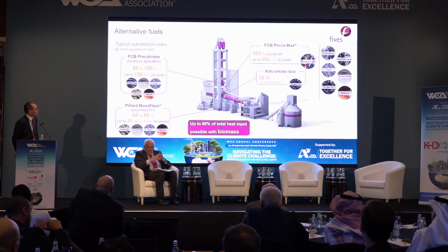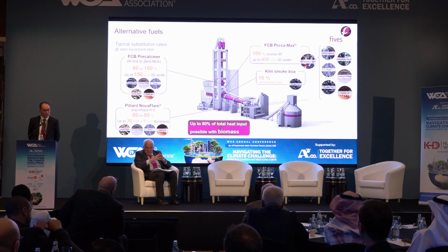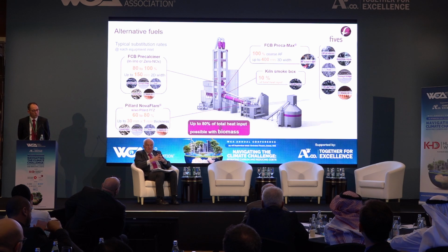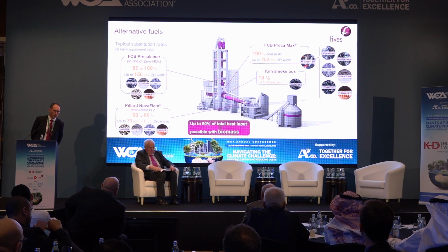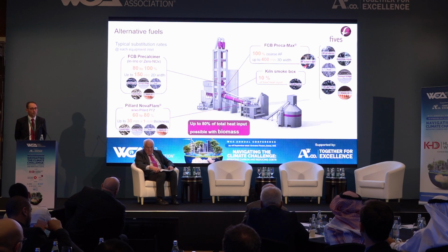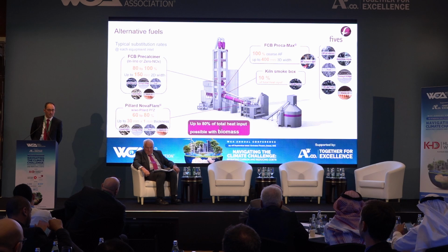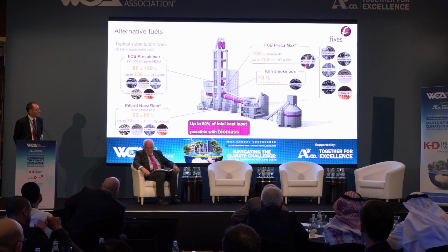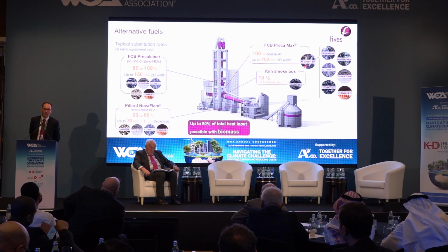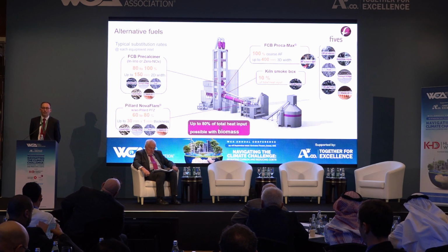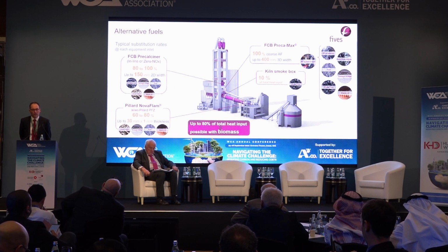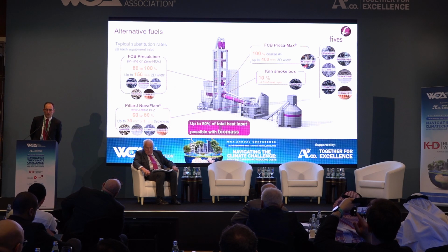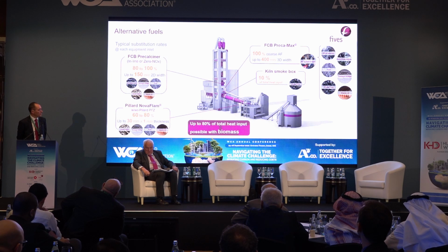You see in our precalciner, we can go up to 150 millimeters in 2 dimensions. You have also the possibility to introduce a small amount in the smoke box. You have also the possibility to introduce alternative fuel in the main burner. But you have also the possibility to introduce coarse alternative fuel. And when I say coarse, I speak about 400 millimeters in a dedicated calciner, which is inline, which opens a new range of possibilities, reducing the needs of pre-processing of your alternative fuel. Instead of shredding to 20 or 40 millimeters, you can put 400 millimeters in your cement kiln line.